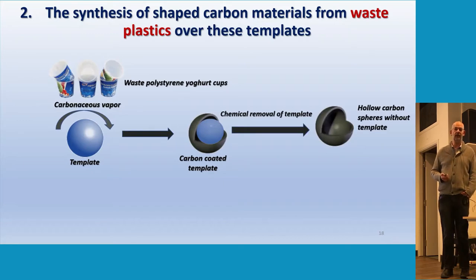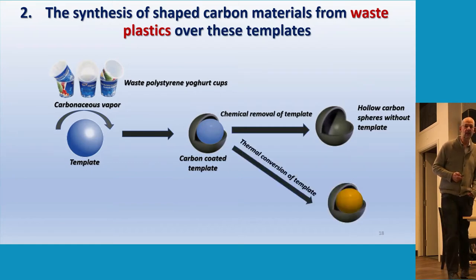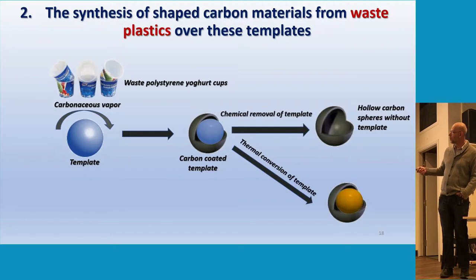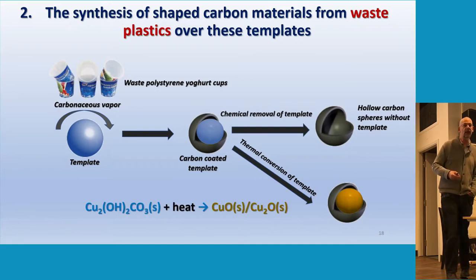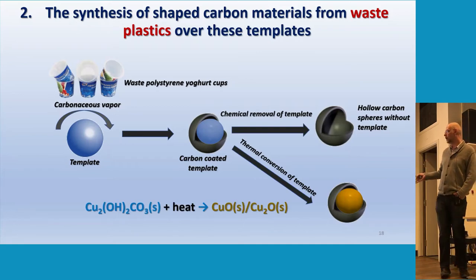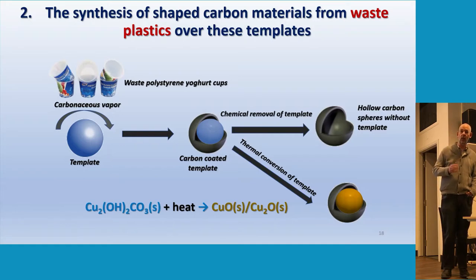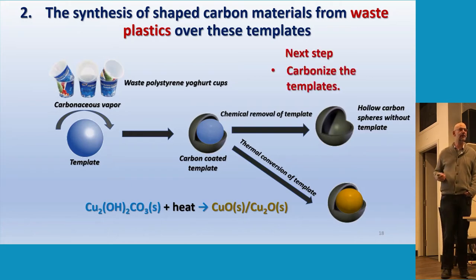After that, you could decide whether you want to remove the template or not, in which case you'd be left with hollow spheres, hollow carbon spheres, micro or nano. We're still at the stage where we're developing this. Or alternatively, by using heat treatment, you change the internal template to something else. In this case, we are aware that when you heat treat the copper carbonate, it actually forms either copper(I) oxide or copper(II) oxide. There is a fundamental reason for that, and I explained that to you just now. So our next step would be to carbonize. We were going to do this this week, but it's been a pretty hectic week, so we'll probably start with that next week. So we're still in the early stages of doing this.